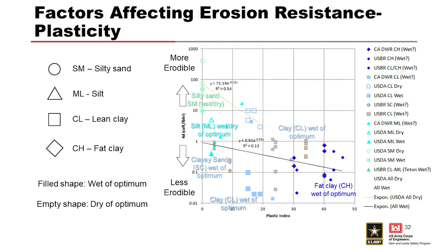All right, what about plasticity? So generally, erosion resistance increases with an increase in plasticity index for both coarse grain soils and fine grain soils. But this is especially true for soils with a D50 of less than 0.3 millimeters. So in fine grain soils, erosion resistance increases with an increase in the plastic limit of that soil. Now, this influence was more pronounced in the EFA testing than it was in the jet or the HET testing.